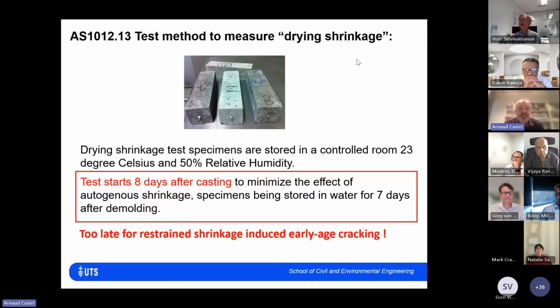So that test is organized such that for the first 24 hours the specimens are in the molds, then they are demolded, and they spend 7 days in the water. And then the first time we get a measurement of shrinkage is day number 8. So it's basically too late. It's after the period we are interested in, the first 7 days after the batching of the concrete. So that's a problem. It's not timely, let's say.